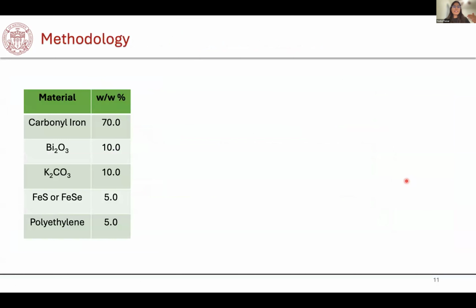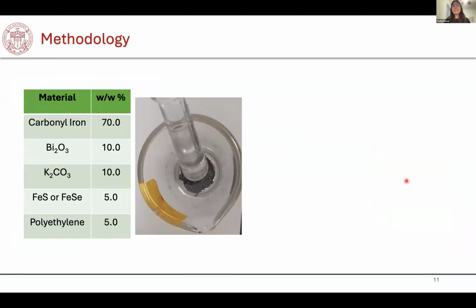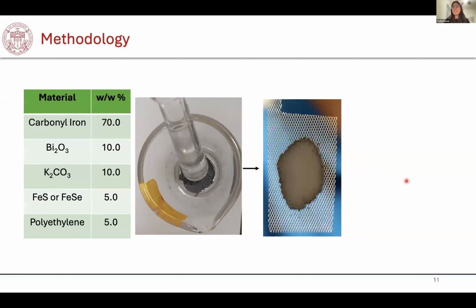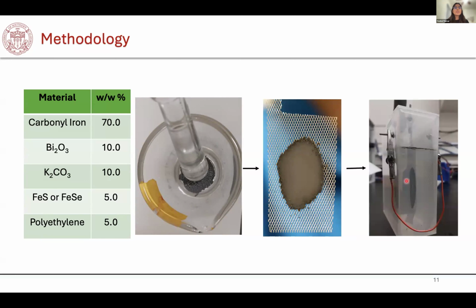To make my cells, I start by mixing these five components and grinding them in a mortar and pestle. 70% by weight of this is carbonyl iron, and 5% by weight is the active additive, which is iron sulfide or iron selenide. Once I have this completely ground, I place it on a nickel mesh, which acts as a current collector, and hot press this assembly. After hot pressing, I set up this three-electrode cell, and now I'm good to go with testing these additives. Once the whole cell is set up, I do the formation of the electrode, which is a very crucial step.